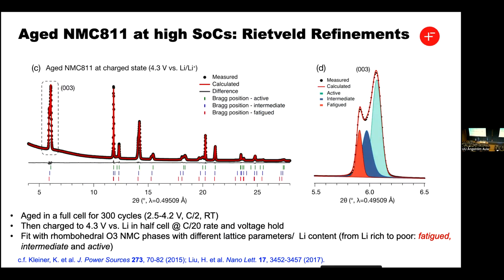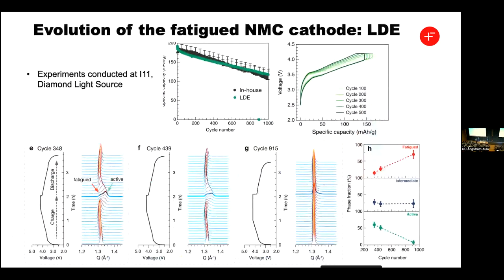This is obviously a simplistic decomposition, but it's a good one to start with. He had one that behaved like the normal phase, which we called the active material. Then the fatigue phase was the one that got stuck and didn't collapse. And there was an intermediate phase. Then he went back, and periodically, every month or so, we got a chance to look at this battery, so we were able to track the growth of the fatigue phase as a function of cycling. By the time you got to about 900 cycles, pretty much all of this phase is fatigued. In other words, it doesn't want to collapse.